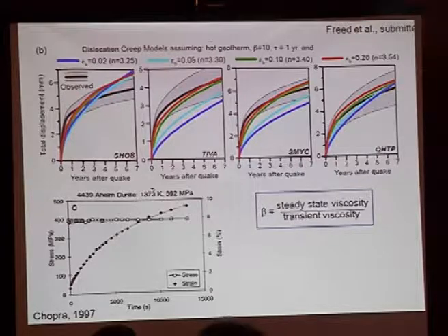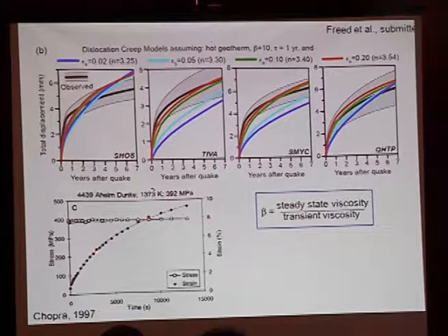And so here's a figure down here that shows this type of transient creep response for olivine. This is a dunite deformed at 1100 degrees. Here's strain on this axis, and the black line is the strain. This is a paper from Prem Chopra, and what Prem did was he was running a deformation experiment, then he cranked the stress up to 400 MPa and just kept it constant. Then you see the strain varying as a function of time. If it was steady state creep, the strain versus time would be a straight line. But you see that it's becoming less and less steep with time.